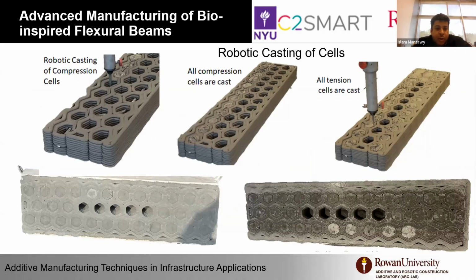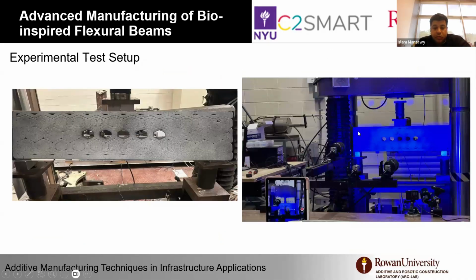So you can see, comparing the color of the concrete, the cast and the print are very similar. This is very critical because it allows the two materials to have the same rate of hydration and fuse nicely. So we end up having a 3-foot-long by 9-inch-deep, 3-inch-wide beam that we printed with different techniques, including cable reinforcement and some regular rigid reinforcement. One of those beams, or a few beams actually, were tested at Lehigh University, and we did a lot of digital image correlation testing on them.